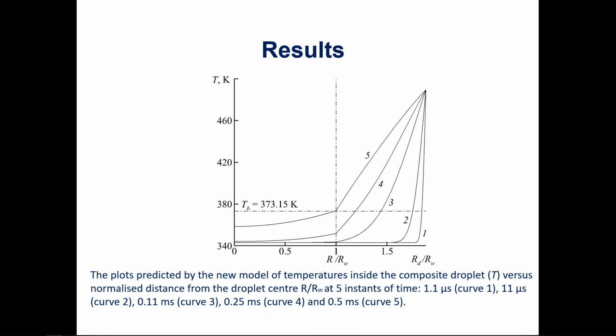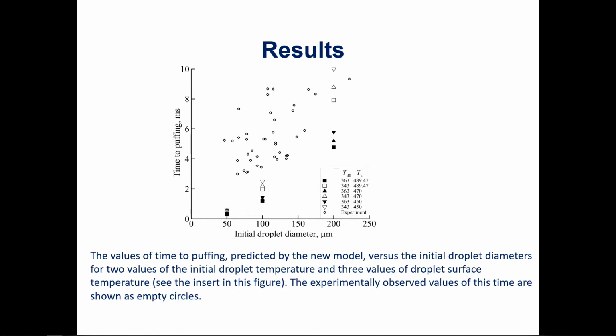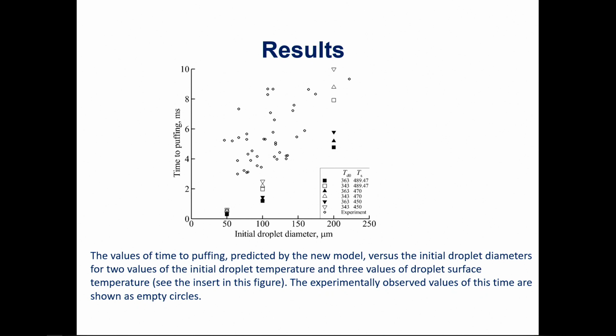And once we have prepared a number of curves like this, we were able to plot the time to puffing or time to microexplosion for different values of surface temperature and different values of the initial droplet temperature on this graph. This is the initial droplet diameter, and these are the values of time to puffing, which is assumed to be equal to the time to microexplosion, as a function of the initial droplet diameter. And on the same plot, we put the experimental results. And clearly, we couldn't get a one-to-one correspondence between experimental and modeling results. But at the same time, we have a correct order of magnitude. And also, we were able to show that our model at least predicts the minimal value of the delay time.